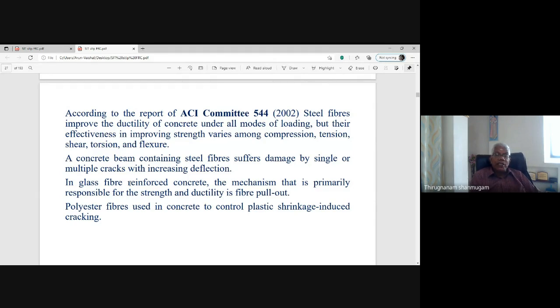Polyester fibers are used in concrete to control plastic shrinkage induced cracking. This polyester fiber is also similar to the glass fiber, with a smooth surface. So fiber pullout is coming, but this polyester fiber has very low strength, and it will not contribute to the improvement in tensile strength or flexural strength or ductility. But it contributes to the action of crack arrestor. So polyester fibers such as Recron 3S fibers are used in concrete to control shrinkage-induced cracks, plastic shrinkage cracks or drying shrinkage cracks.